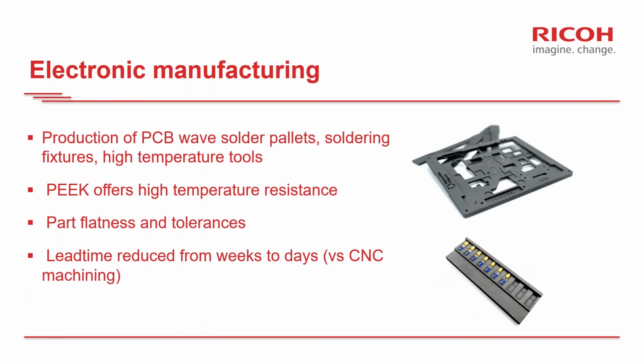As mentioned in the previous slide, one of the main applications where this type of composite parts made with the technology have been very successful is the production of PCB solder pallets, soldering fixtures, and generally high temperature tools for the electronic industry. In particular, with PEEK-based composite, thanks to the high temperature resistance and the low coefficient of thermal expansion of the material, this enables the use of a soldering iron on the fixture without damaging it, and enables holding the component in place during the process. And actually, the fixtures don't get damaged during the process, and so they can be reused.